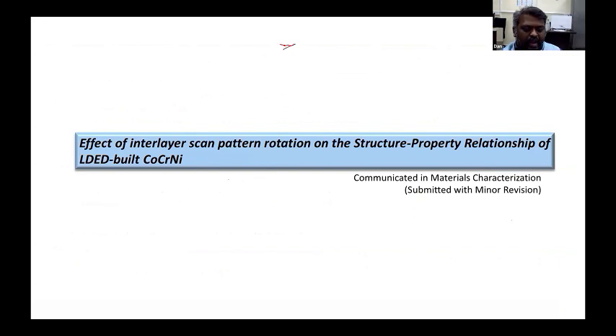Okay. So now the second study, our objective is we try to change this scan pattern. We try to rotate this scan pattern. Like in the previous case, we did not change the scan rotation. It is at 0 degree, meaning layer by layer it will go in a similar orientation and deposit. But in this case, the scan pattern will keep on rotating.